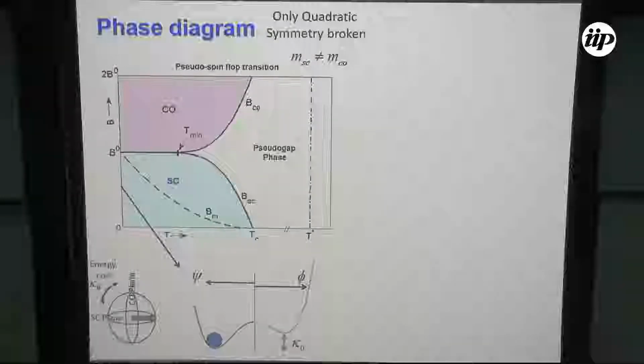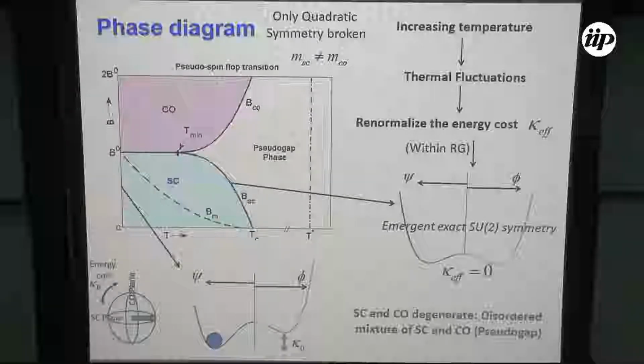So if we are at lower fields, lower than this B0, we are in the superconducting phase. Let's increase the temperature. Increasing temperature will increase the thermal fluctuations in the system, as she was talking about. So the pseudo-spin, which was lying in one direction, will now start fluctuating, and there would be one point where, within this renormalization group treatment, this anisotropy gets renormalized in this RG process, and they become exactly equal at this